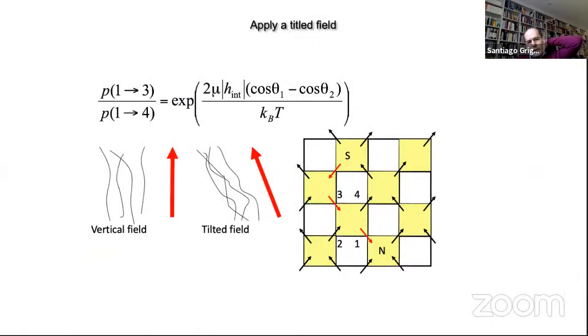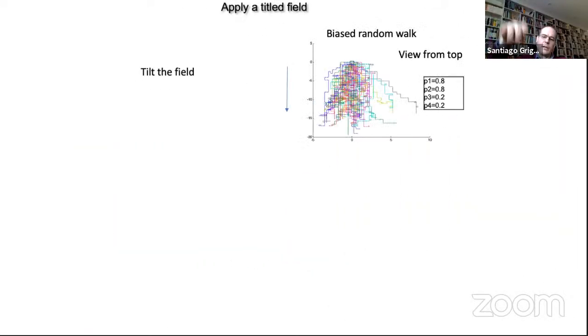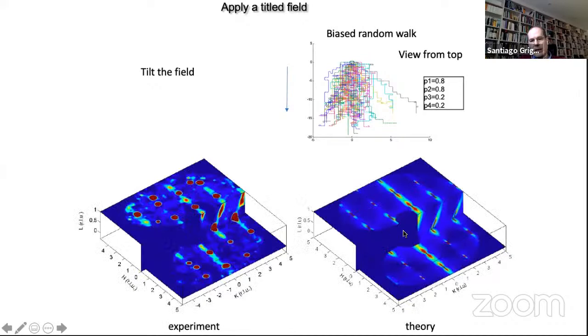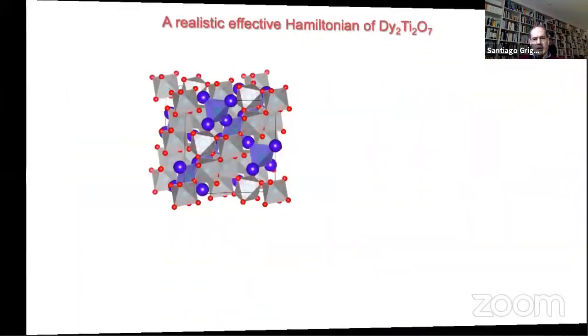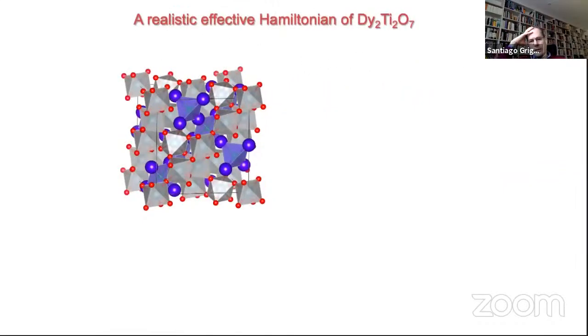But if you're not fully convinced, or we were not fully convinced, you can think about this now. Now you say, okay, I'll tilt the field a little bit. And what that would do is, instead of having these completely random walks along the field direction, I will have biased random walks, right? So if I look from the top, the random walks would tend to move towards one direction. So now when I calculate the correlation function for that, that would give me a correlation function which is elongated along one direction, right? Because there's a better defined correlation in one direction than the other. And if you compare that with the experiments where you tilt the field, you see that again, you get something that resembles the theory.